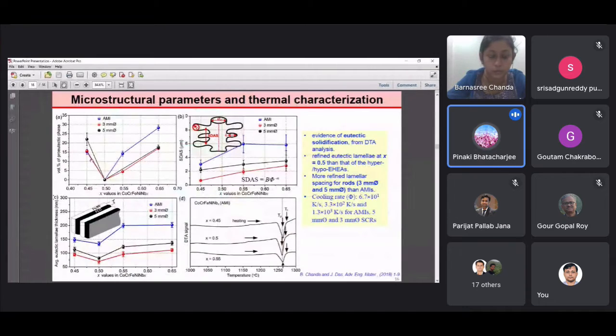Have you determined the fraction? Yes, sir. For hyper eutectic, we have measured. And we have seen that for the as-cast ingot, it varies in the range of 15 to almost 28, something like that, 20 volume percent. Yeah.